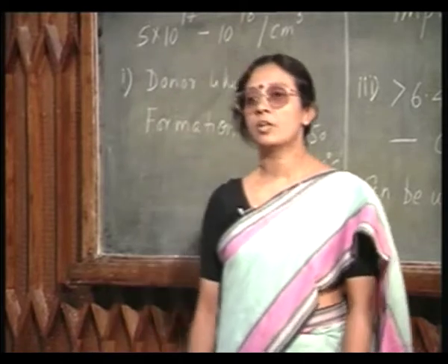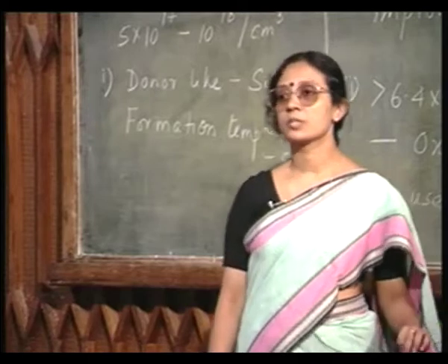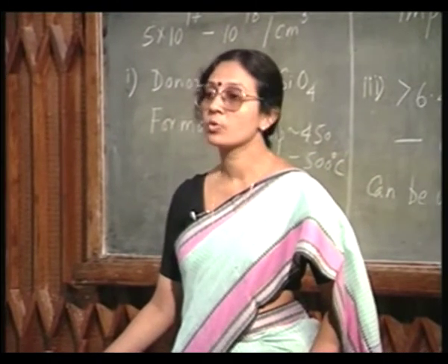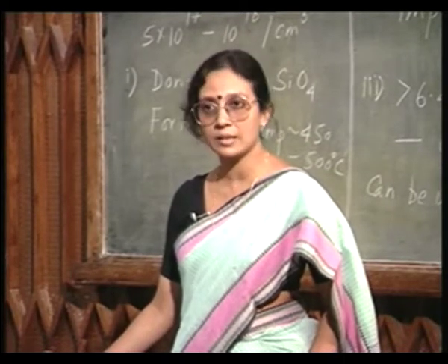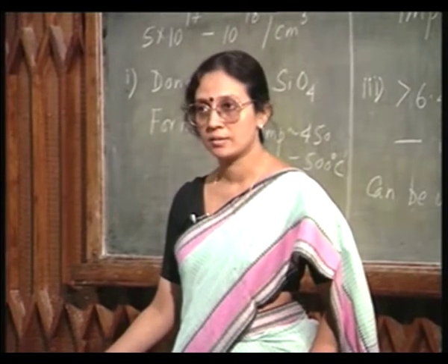However, because of the quartz crucible, there will be some oxygen present in the silicon, and the problem is more aggravated because oxygen has a segregation coefficient greater than 1, so that it will preferentially come inside the silicon.